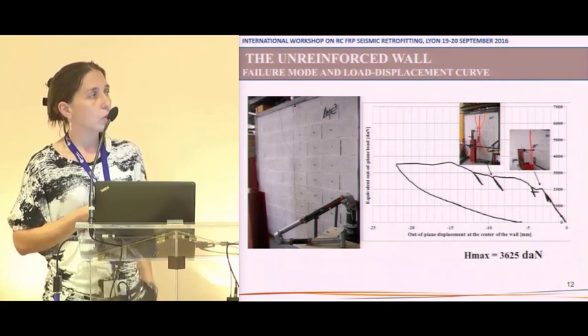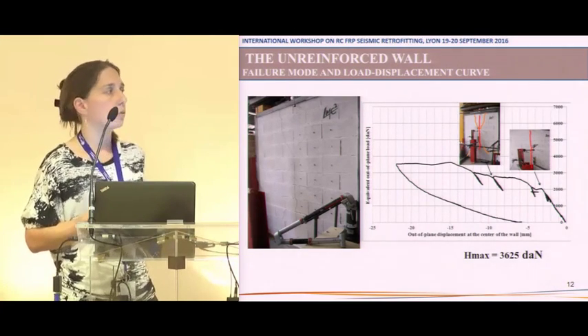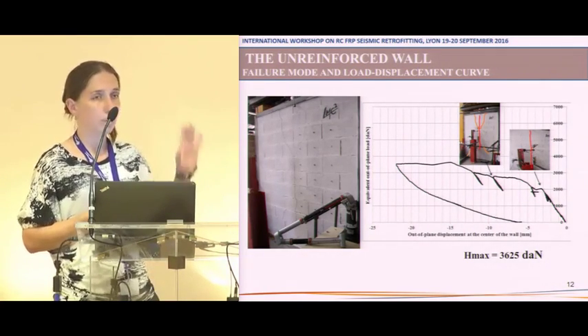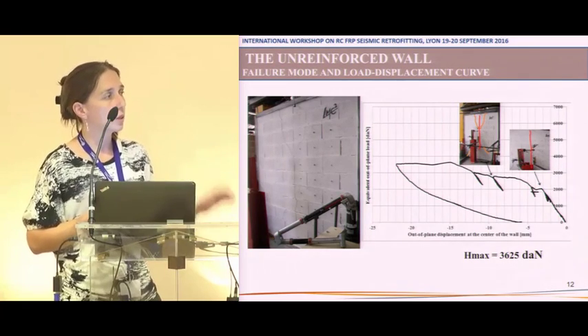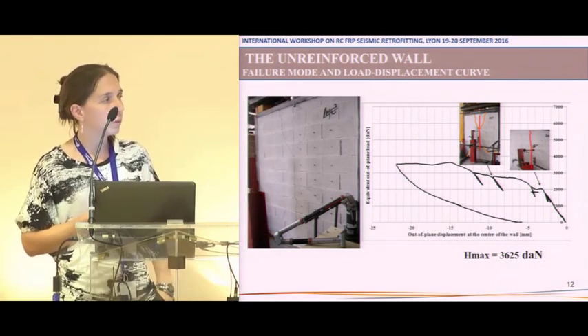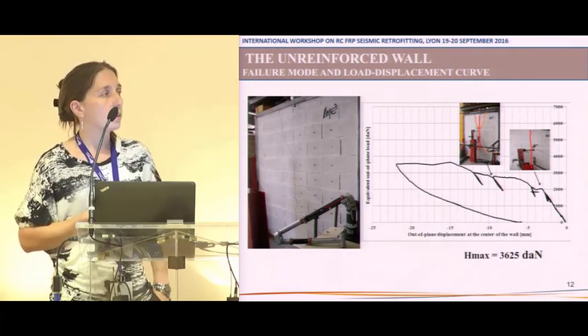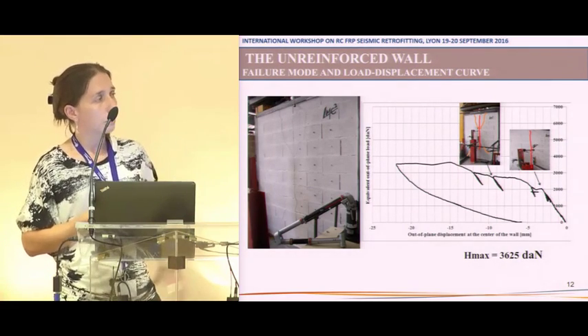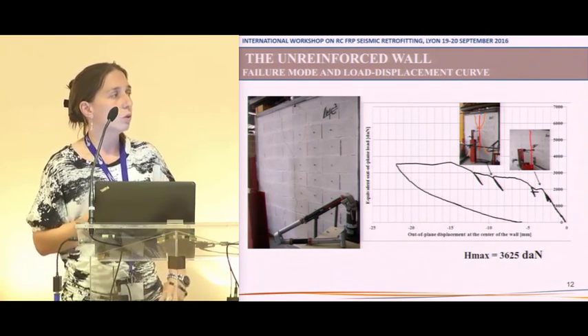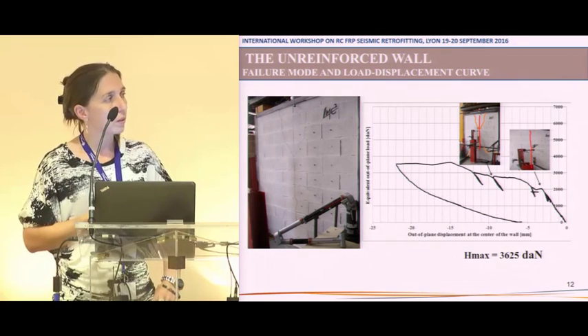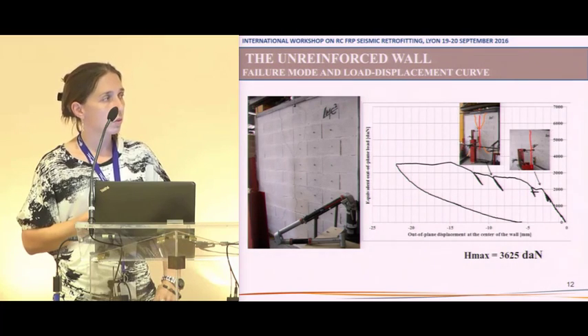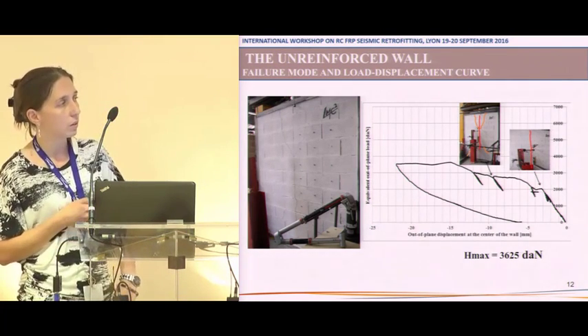We have here the equivalent out-of-plane load given by the force transducers and the out-of-plane displacement at the center of the wall, directly given by the laser sensor. We can see a first linear zone where the wall integrity is preserved. Then a vertical crack appears, which marks the beginning of the nonlinear zone.